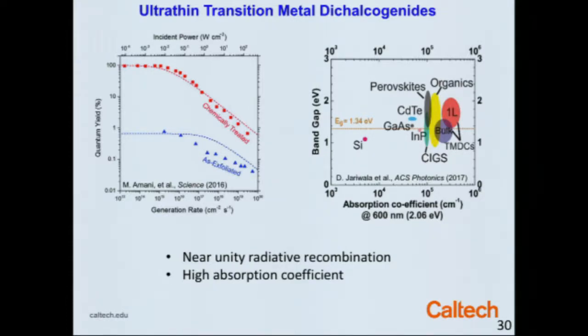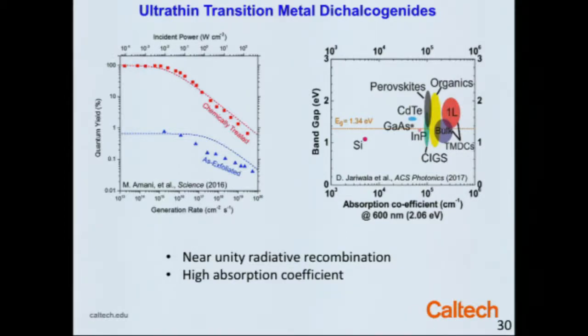This is my first exposure to molybdenum disulfide. When I started at Caltech, I built an ultra-high vacuum system for doing experiments, and it was used as galling grease—a non-hydrocarbon lubricant you could use to lubricate the bolts on your stainless steel vacuum chamber. So this is galling grease that has a luminescence yield of 100%.